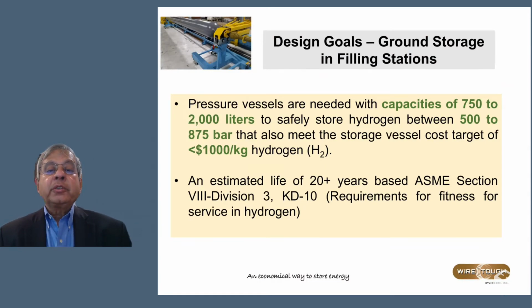Now, if we just focus for a minute on filling stations for hydrogen, what are the associated design goals? Pressure vessels are needed with capacities of 750 to 2,000 liters to safely store hydrogen between 500 to 875 bar that also meet the storage vessel cost target of less than $1,000 per kilogram of hydrogen stored. An estimated life of 20-plus years based on ASME Section 8 Division 3 KD10 requirements. These are requirements for fitness for service in hydrogen.